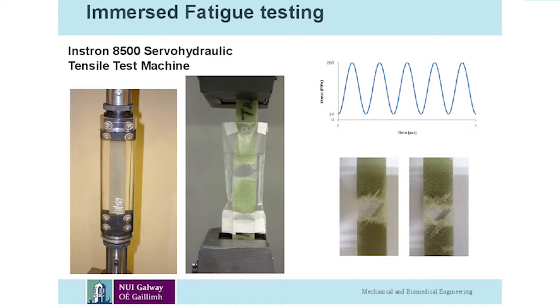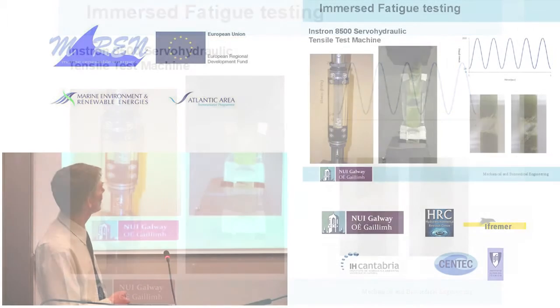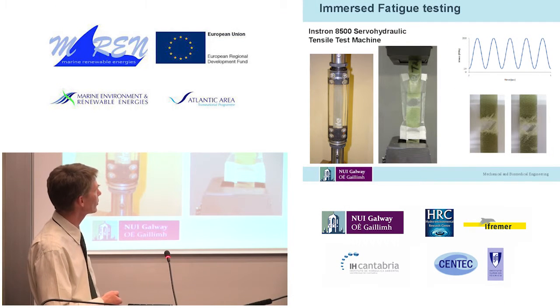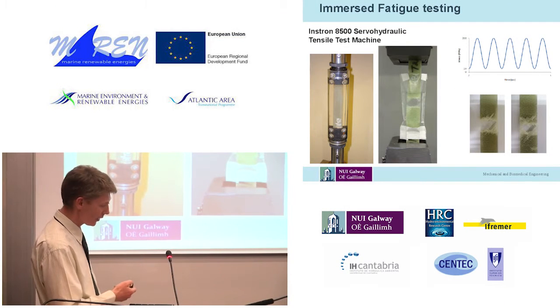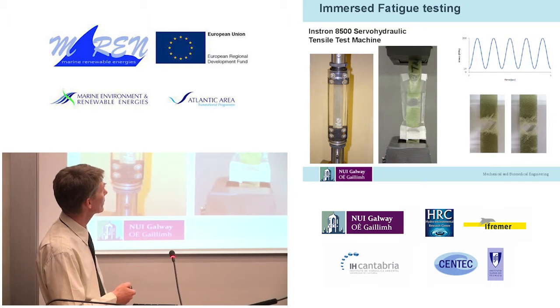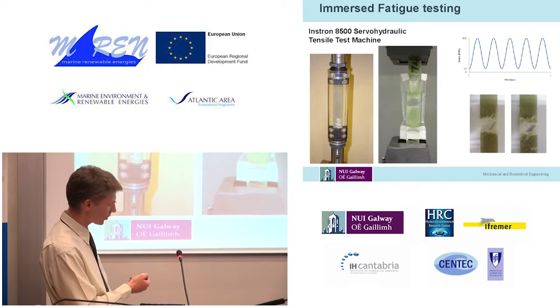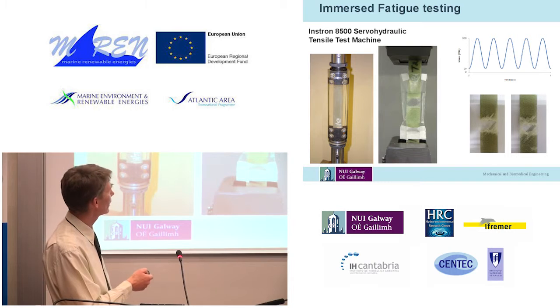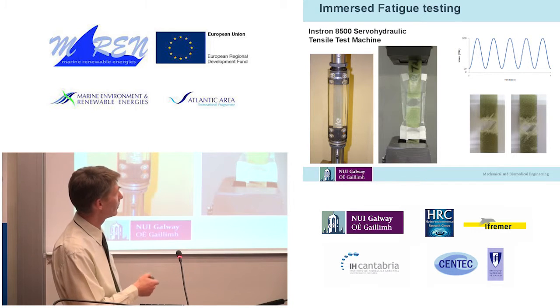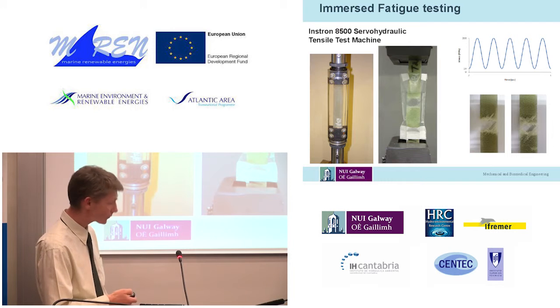So I did some fatigue testing of the coupons on a servohydraulic test machine, and we tested them in what we call tension mode here. So we went between about 200 MPa and 20 MPa in a cycle about 5 times a second.